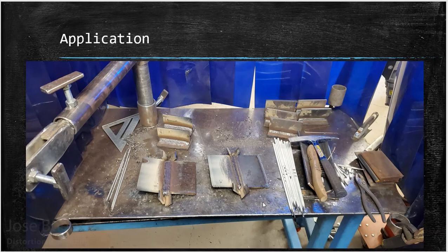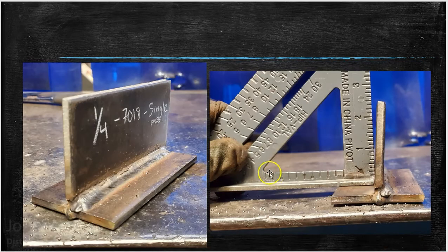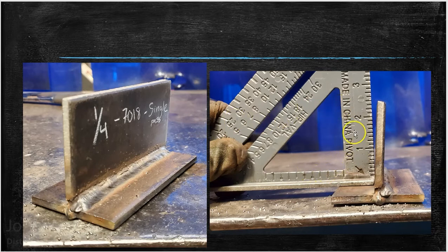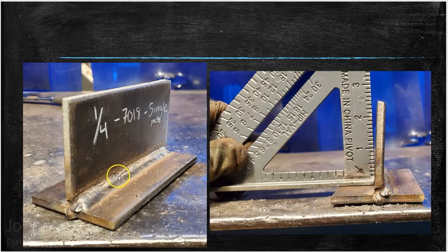In the welding shop, I welded some joints to give you an idea of how distortion can occur and how it looks. First, I made a T joint out of one-quarter-inch carbon steel using 7018 at about 140 amps with one single pass. After letting it cool for about 45 minutes to where I could touch it with bare hands, I measured it with a speed square for squareness. The vertical plate had pulled itself over toward the weld — quite a bit of distortion, perhaps because the current was a little too high for the thickness of the metal.